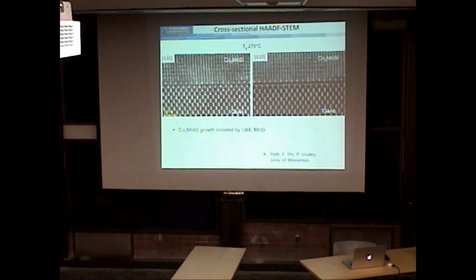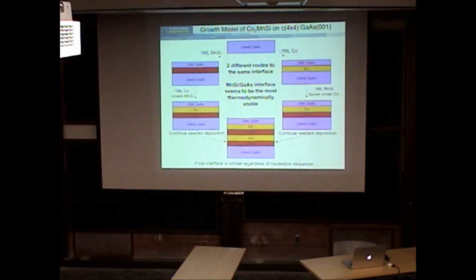Sorry, Chris, back to this. So you're capping with gallium arsenide? No, this is a result of... One of these burrowing things? Well, it's not really burrowing. I think what's happening is the top surface monolayer is reacting a little bit and the gallium and arsenic are riding up. And it's basically about one monolayer of coverage, or submonolayer.